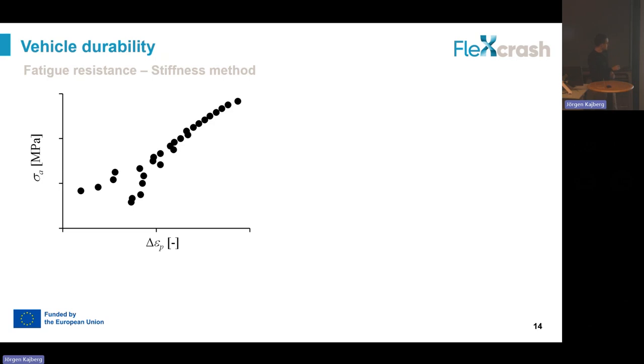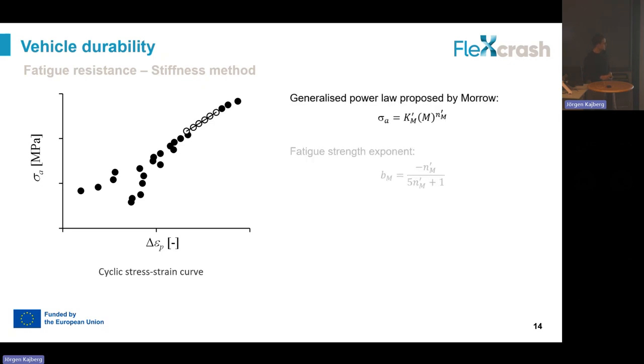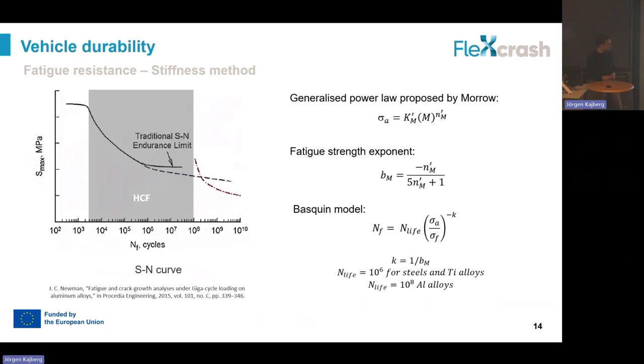Then we can also use the same data, but in this case we are just switching the axis, and by using this data and applying these general formulas, we can obtain a first approach of the S-N curve, so this Basquin curve, and define, by only using one specimen, the fatigue limit and also the S-N curve, or at least the first approach of this, for these different materials.